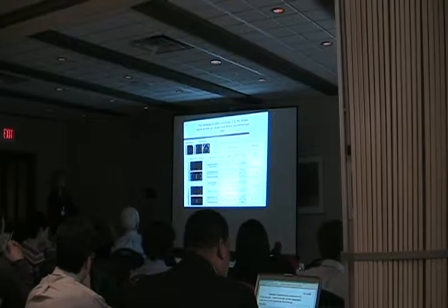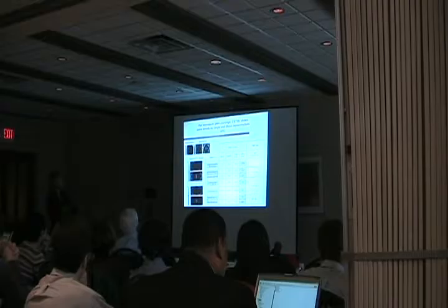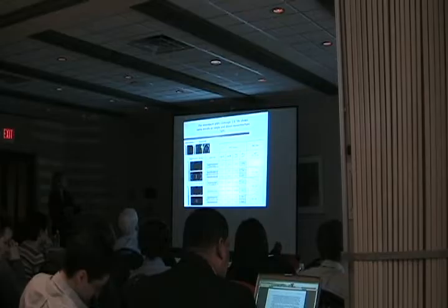And if we go through and very systematically calculate the local fields, exactly what we would expect, the field enhancement, |E|^4, on the surface of the particle, surface averaged, because everything is coated with a monolayer of molecules, and we actually compare the experimental counts to what we can obtain theoretically. We can even test for roughness to see if roughness is important, as shown here. So this was an FDTD simulation that matched the Mie scattering calculation. And if we compare the two, we find that, in fact, dimers win, but not by a whole lot. If you look at the actual surface averaged signal, then yes, this is a much larger field, but over the surface average, we have a lower field over a larger surface area, and it's about a factor of 10 smaller in strength, less of a difference than a dimer.